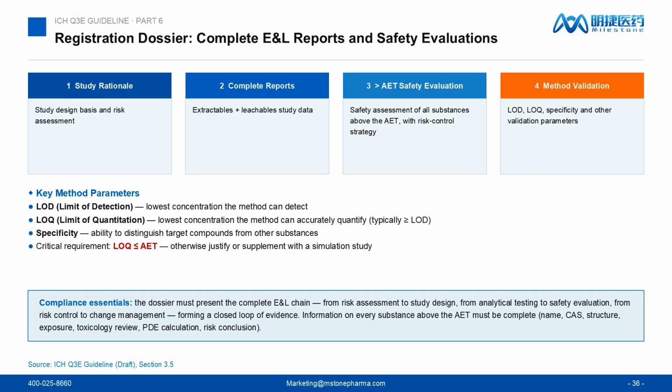And the critical rule: your LOQ must be at or below the AET. If it isn't, your study cannot demonstrate that compounds are below the AET, a logical hole that triggers deficiency letters. Fix it with a better method, or justify and supplement with a simulation study.